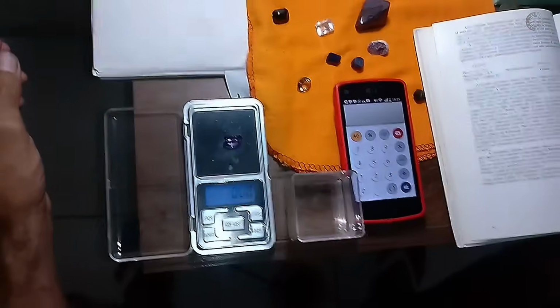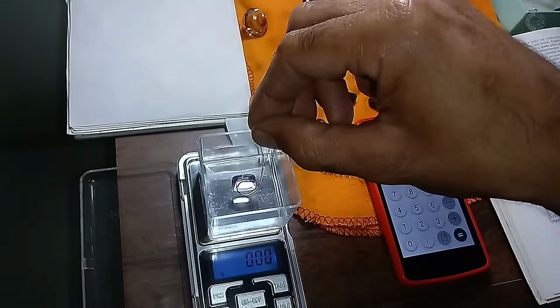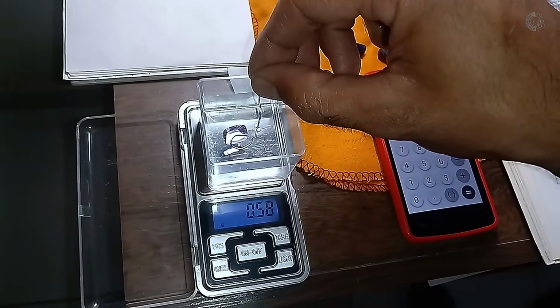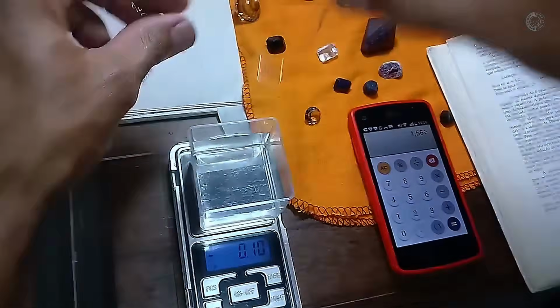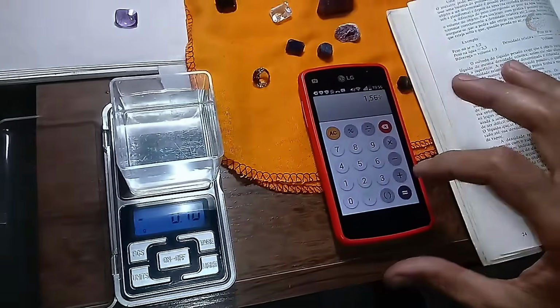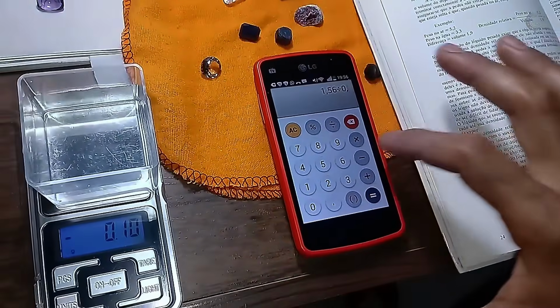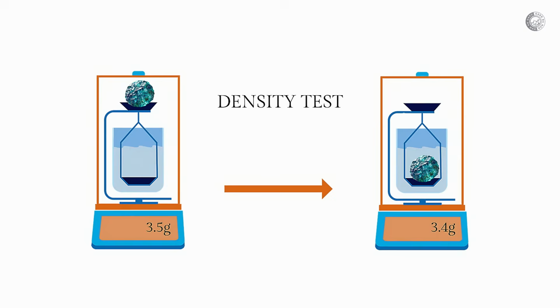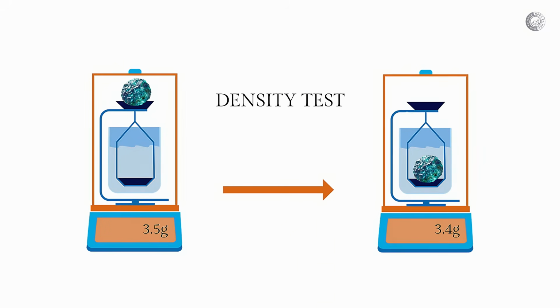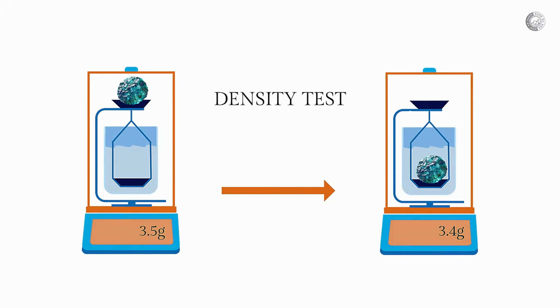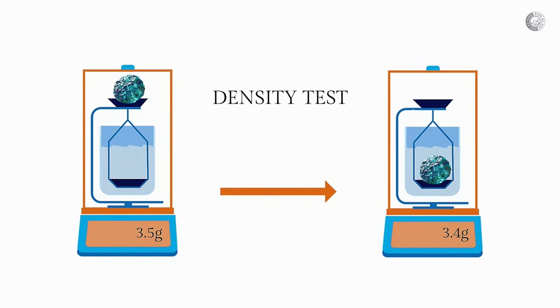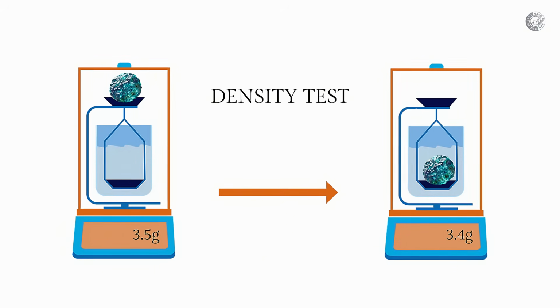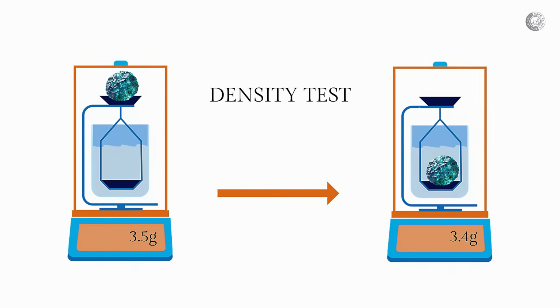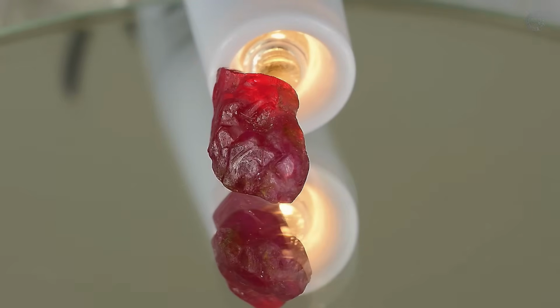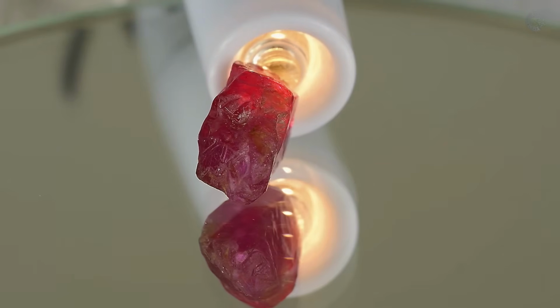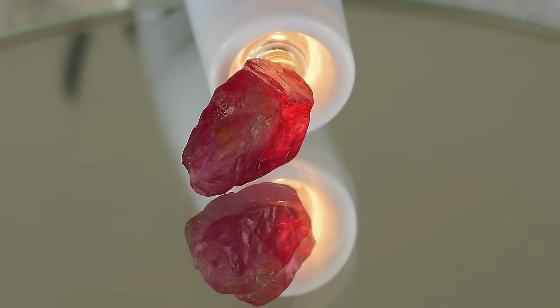Then fill the container with water to a marked level and carefully place the stone inside, watching how much the level rises. That rise corresponds to the volume displaced, in milliliters equal to cubic centimeters. Now divide the weight by the volume, and you'll have the density in grams per cubic centimeter. If the result falls between 3.5 and 3.53, you have strong evidence it could be diamond. If it's closer to 2.65, it's quartz, which is much lighter. If it's above 5.5, it's likely cubic zirconia, easy to mistake by looks but revealed by its excessive weight. Sapphires and rubies, which are corundum, fall between 3.95 and 4.1, just a bit heavier than diamond,